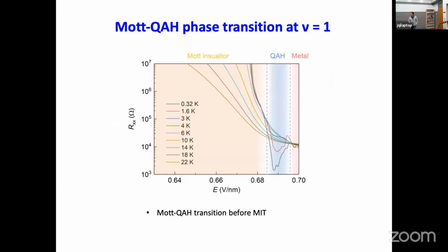Well, you can also tune the electric field by keeping the filling factor fixed equal to 1. This is the RXX map as a function of the electric field at different temperatures. The Chern insulator only happens in this small phase space here. You can see that the RXX drops significantly with decreasing temperature, corresponding to the onset of the chiral edge state transport, and that's why the RXX drops significantly here.